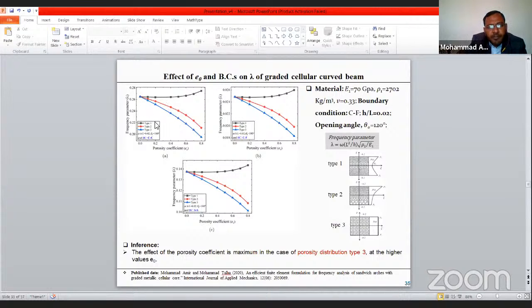And we found that on increasing the porosity coefficient, the frequency parameter increases for type 1, but for type 2 and type 3 it is decreasing. It means the effect of porosity coefficient depends on the type of porosity distribution taken. And in case of type 3, it is giving maximum effect at higher values of porosity coefficient e naught. Let's say at 0.8, it is giving maximum deviation from the standard one.